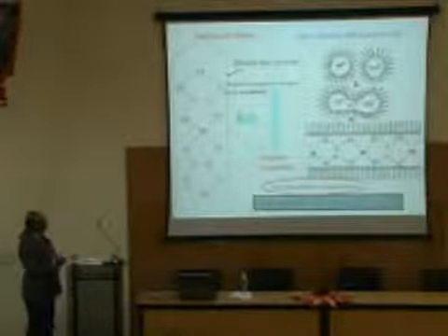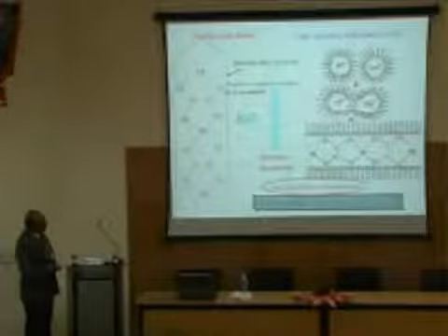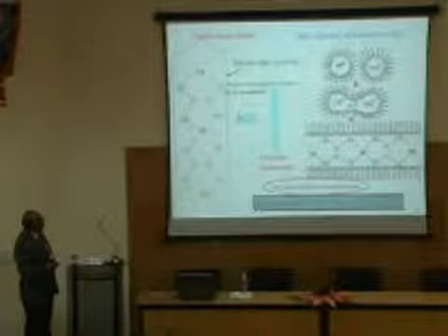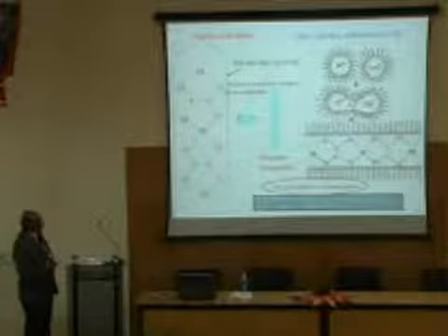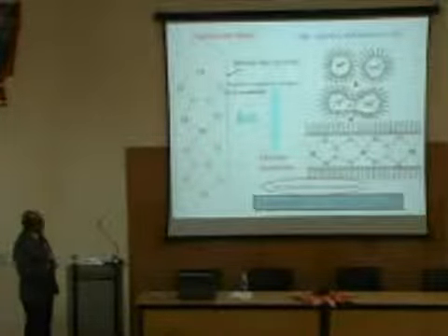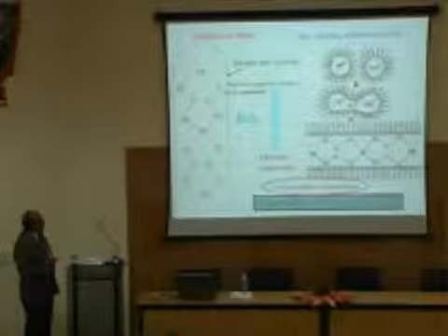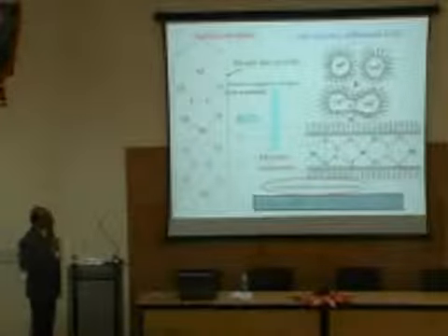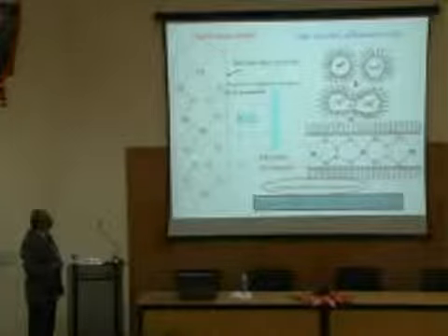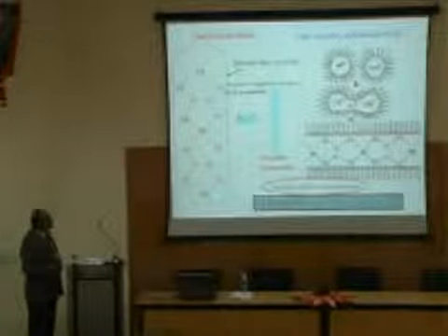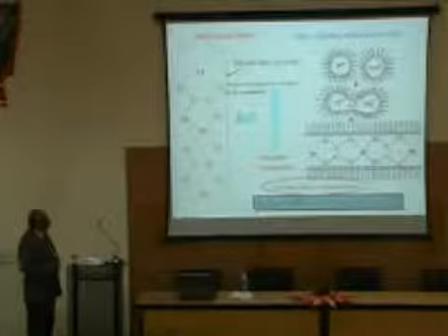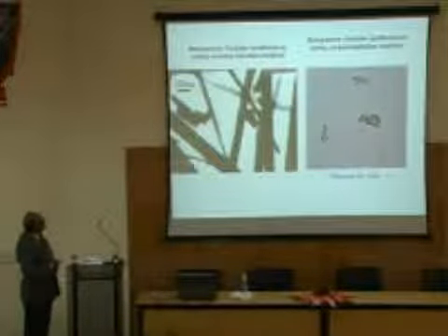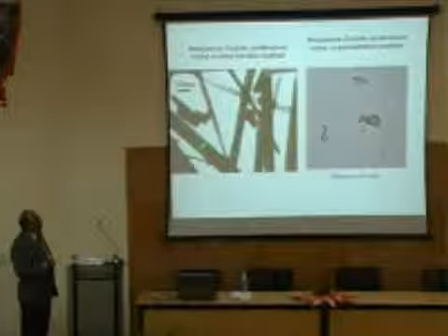So this is a typical case of making rods of some metal carboxylates. So we have a microemulsion based on a cationic surfactant, and these rods are aligned because the surface of this rod, because of these oxygens, becomes negatively charged, and these cation surfactants have a positively charged head group which blocks the growth of the rod in this direction. So there is a tendency to form or grow in only one direction. Okay. So you see these rods which have diameter of around 60-70 nanometers, but they are very long.